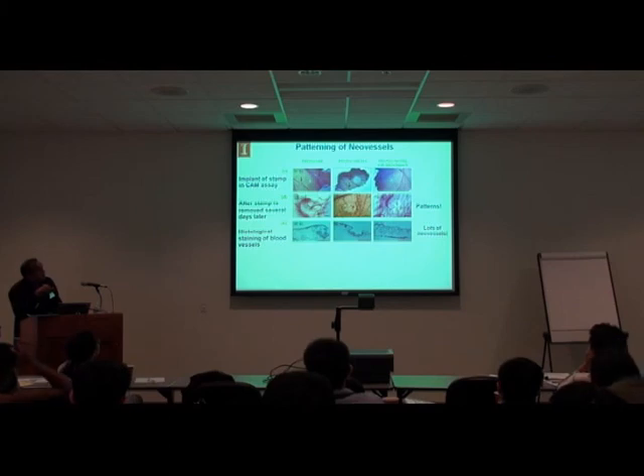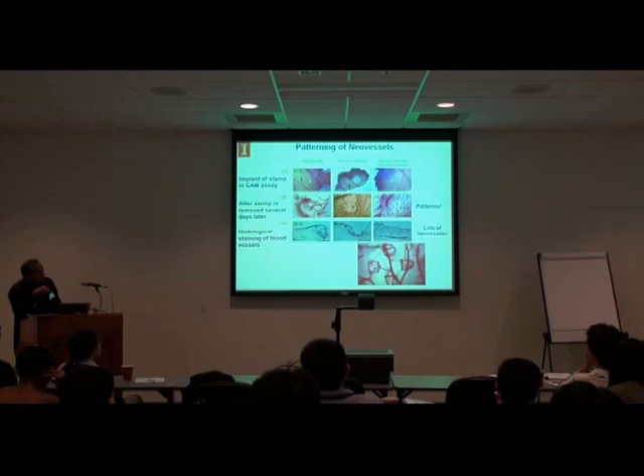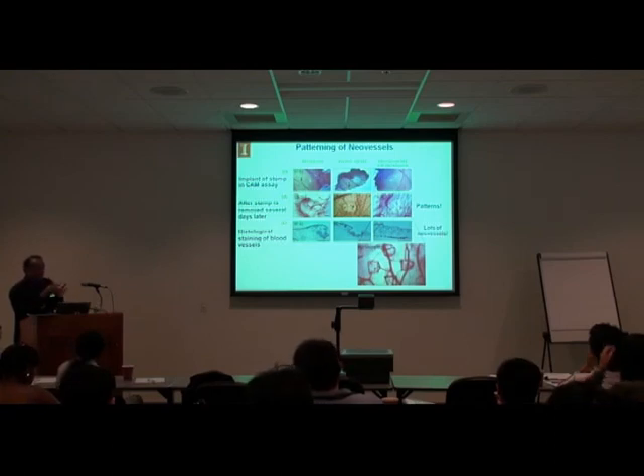And what's very, very interesting is that, so this is the implant of the stamp in the CAM assay. This was the stamp right there. You can see it, right? Everyone can see it. And this is a different material. This is PEG 1000. This is PEG D8000, PEG D8000 with alginate, and this is the PEG D8000 alginate with the microchannels. You can see the microchannels right there in that structure, right? So what's very interesting is that after a week and 14 days, when we take this out, we can actually see the blood vessels forming patterns around this, where the holes were in that stamp. And that has to do with the angiogenic factors diffusing out and creating a concentration gradient and directing the growth of the blood vessels in those regions.